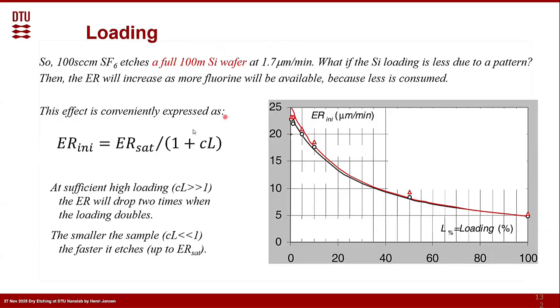This is conveniently expressed as the initial etch rate, let's call it a saturation etch rate, divided by 1 plus a constant times the loading. Well, look first when the loading is very high, then the 1 can be taken out of it. So then it is the saturation divided by CL. So at sufficiently high loading, the etch rate will drop 2 times when the loading doubles. So that's what we more or less used here. 100 millimeter, 1.7. If it would be 50% loading, then it would be 3.4.